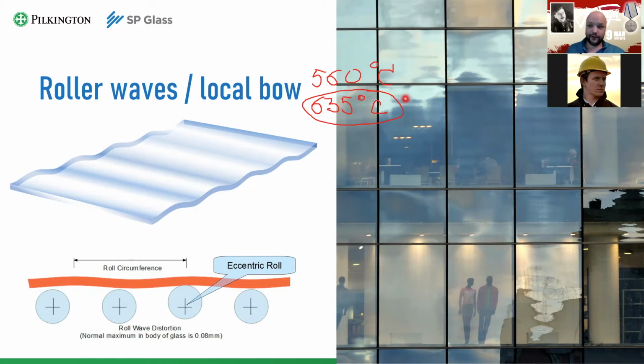For that, I would never advise a 4mm glass as an outside glass if it is tempered. 6mm glass is far, far better. 8mm glass is almost perfect in terms of tempering distortions, price-wise and weight-wise. 8mm glass is almost always optimal if you're not going for very big IG units.